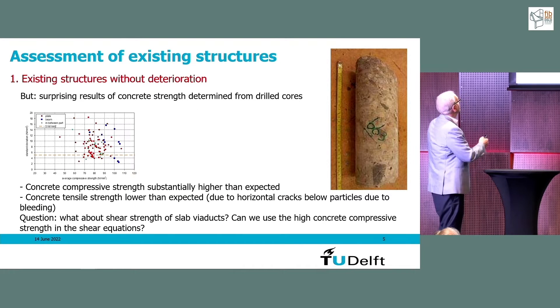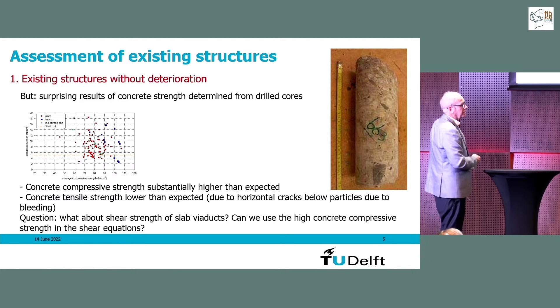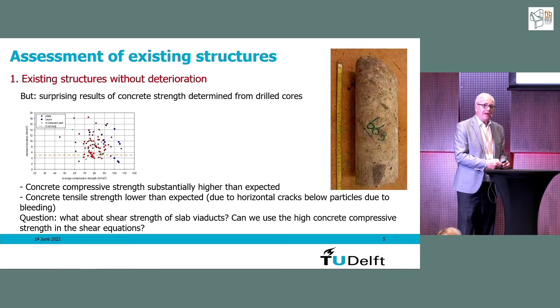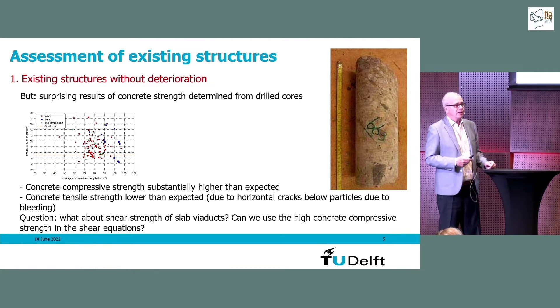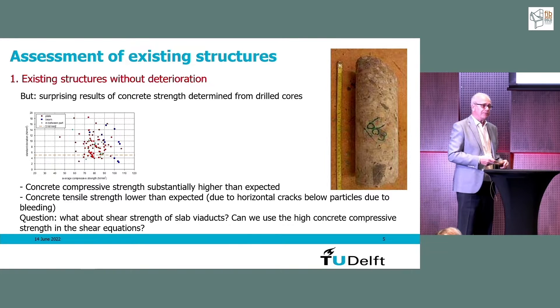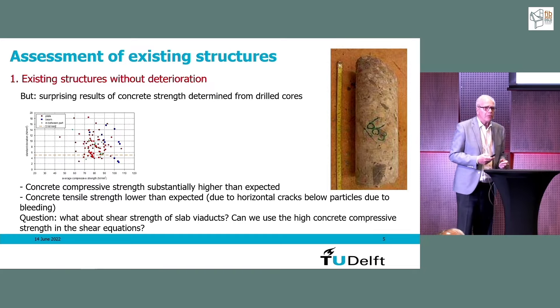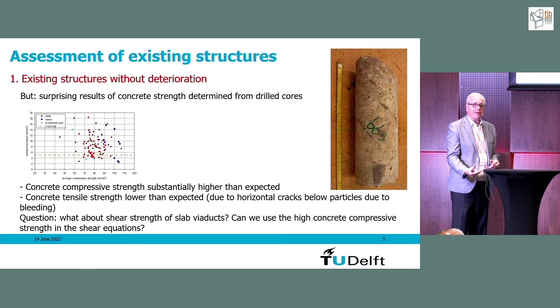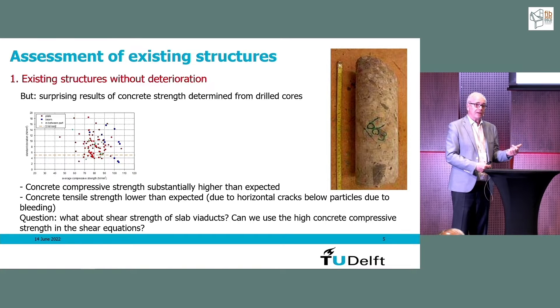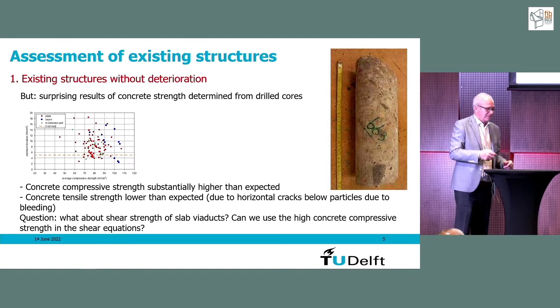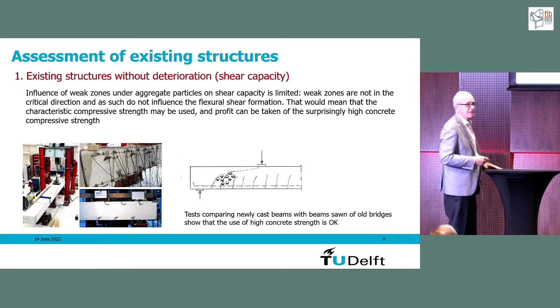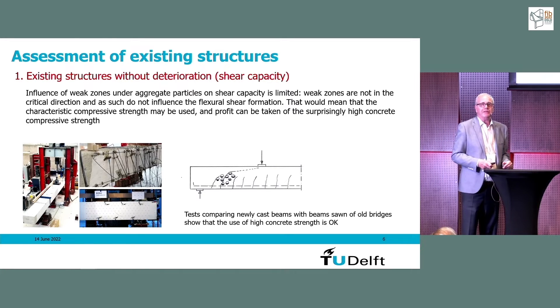The result was very surprising: the average compressive strength — these are cube strength values — was much higher than the capacity required in design 50 or 60 years ago. The splitting tensile strength was also very high. However, the centric tensile strength was very low, and some cylinders drilled from the bottom just dropped off — meaning tensile strength was essentially zero. Since shear capacity depends on concrete tensile strength, this was a critical question.